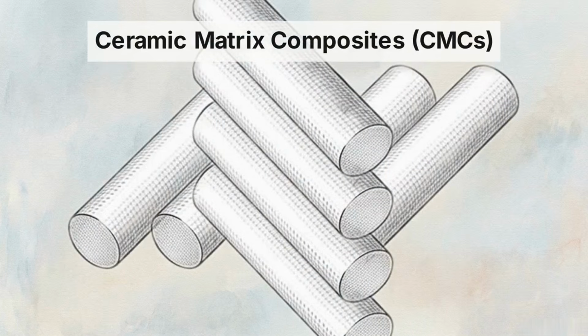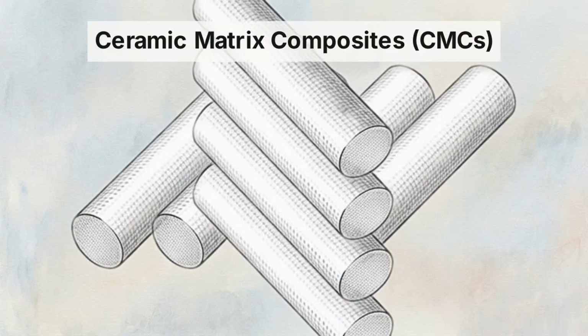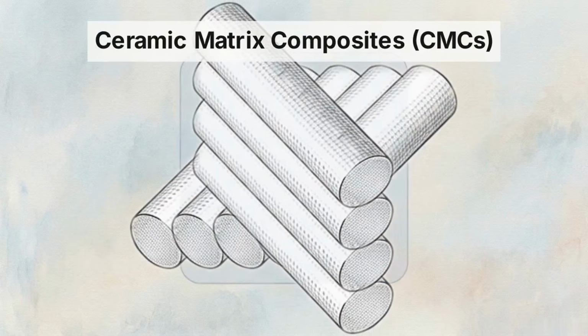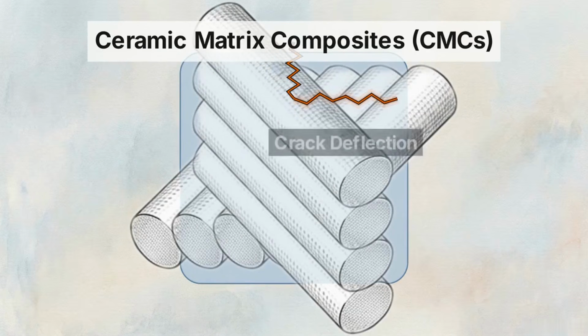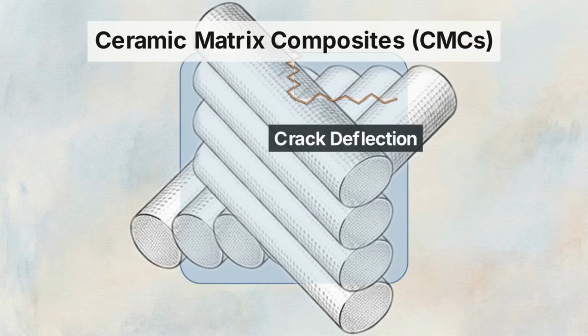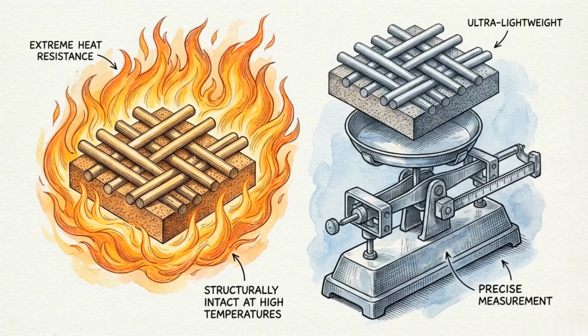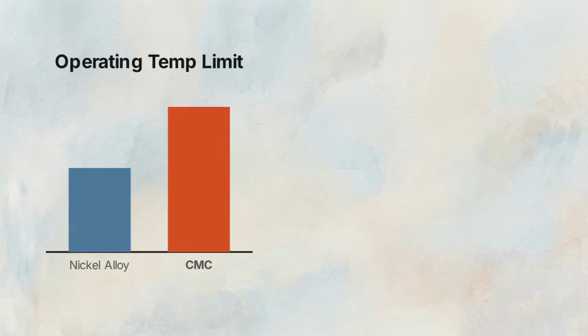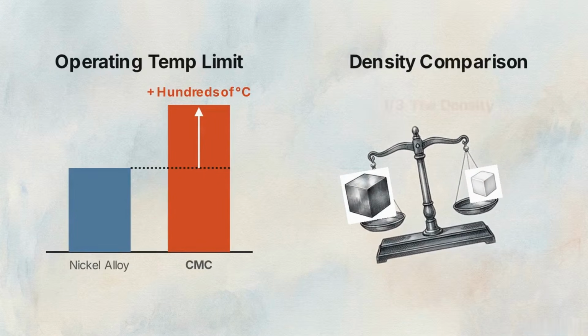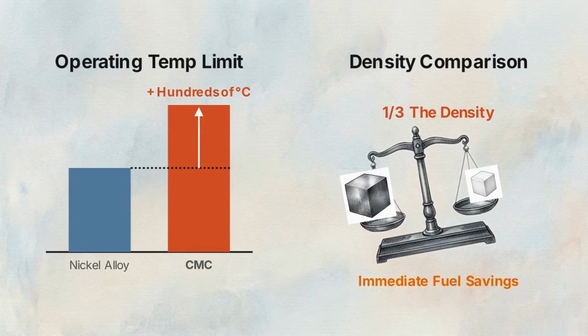But the true successor to the superalloy is a completely different material class, Ceramic Matrix Composites, or CMCs. By embedding rigid ceramic fibers within a surrounding ceramic matrix, engineers have solved the brittle fragility of standard ceramics through a mechanism called crack deflection. These composites offer a massive dual advantage. They can operate hundreds of degrees higher than the limit of nickel, requiring far less cooling air. And because they possess about 1/3 the density of superalloys, the weight reduction translates into immediate fuel savings.